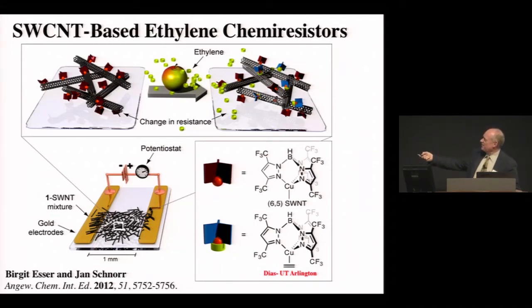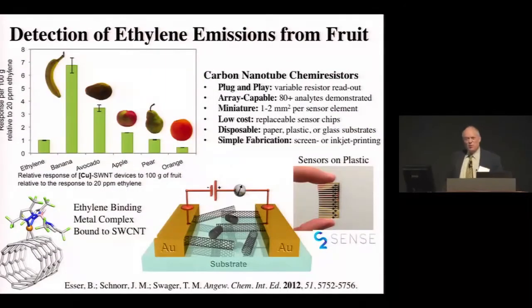So it sticks to the nanotubes, and now we have nanotubes that are functionalized, and we're not really sure. Nanotube research is tricky because, unless we can sometimes make fullerene compounds, we can't take NMRs of them. We have no crystal structures. We have no mass specs. We do elemental analysis by X-ray photoelectron spectroscopy. We do thermogravimetric, infrared, Raman, but we're not really at the same level of characterization you have in the molecular world. But nevertheless, what we believe is happening is this copper sticks to the nanotubes.